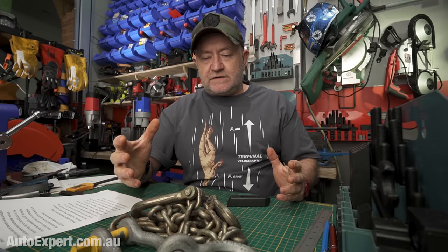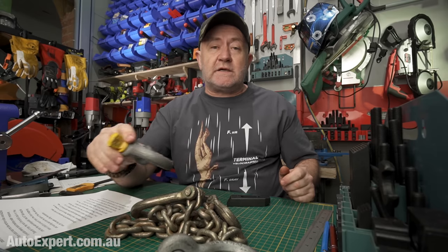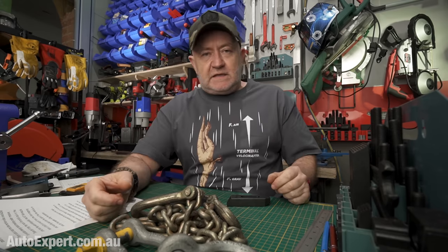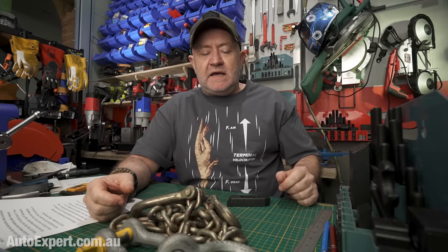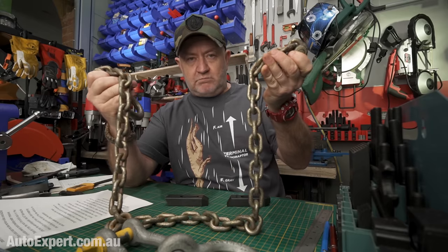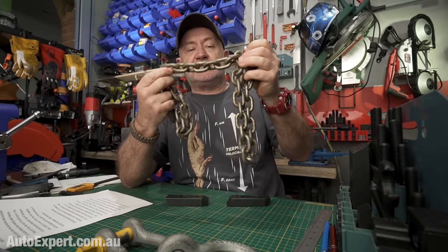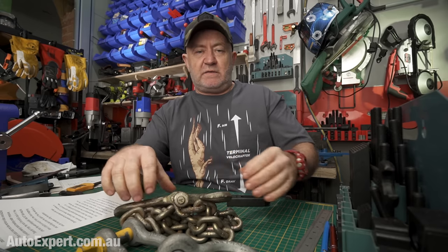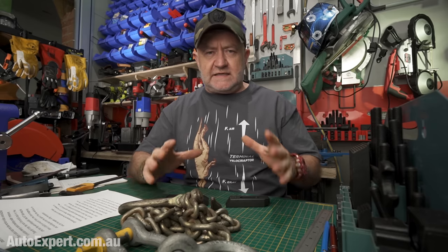The other caveat is that the equipment must not be damaged. If you take an angle grinder to a shackle and cut halfway through the pin, it's going to break earlier. Straps are a little like that too — if you use a snatch strap to pull a tree off a track, straps are really susceptible to abrasion. If the strap goes over a rocky shelf, mechanical abrasion will wear it down. In those situations, a drag chain is more robust — a bit of sandstone is not going to do much to chain made of hard heat-treated steel, whereas it will damage a strap.